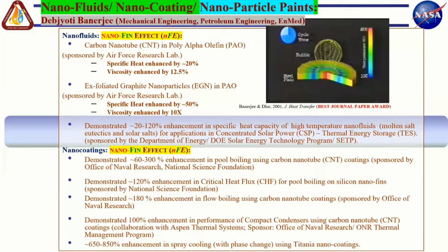Now, in parallel, while I was doing all this work at Air Force Research Lab, in my own lab here at Texas A&M, we were experimenting with nano coatings for enhancing boiling. And so the first time around we tried it, we put nano coatings on heater surfaces using carbon nanotubes. And the enhancement in the critical heat flux was about 60%, and the enhancement in film boiling was about 300%. And to date, our research group is the only one that has film boiling data for carbon nanotube coatings on heaters.